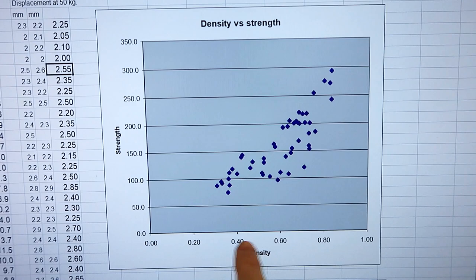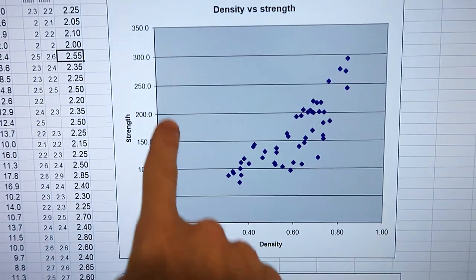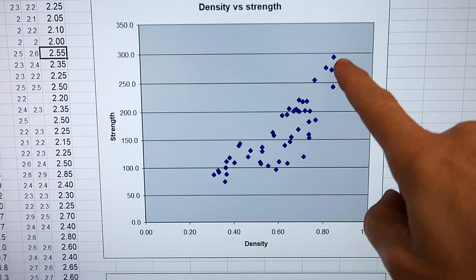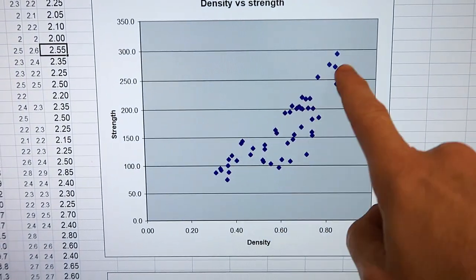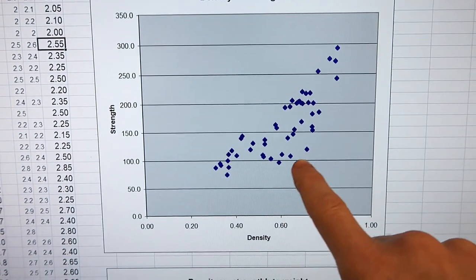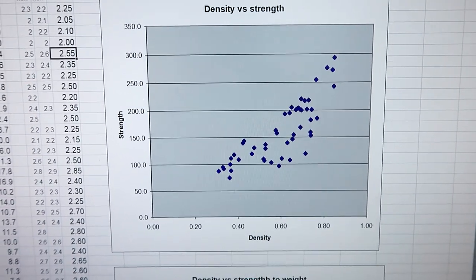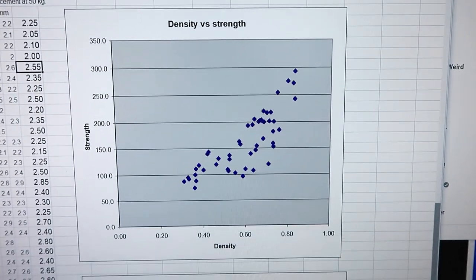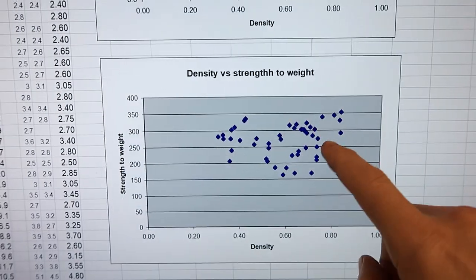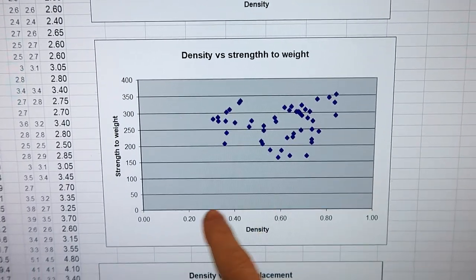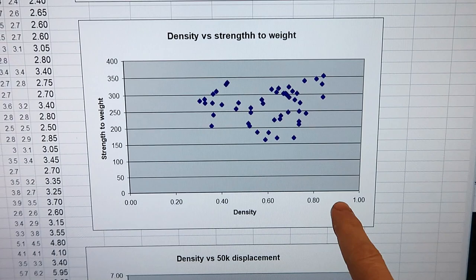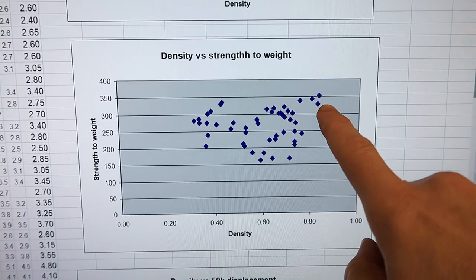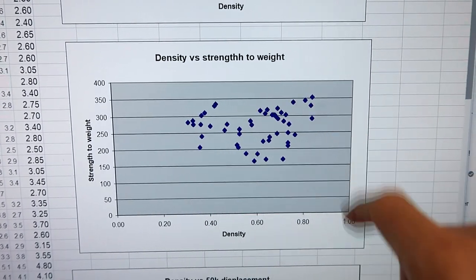And plotting wood density on the bottom versus the ultimate strength, you can see these pretty much follow a line in terms of how well they go. Some of them are suboptimal in that they were heavier but not all that strong. Then I was wondering about strength to weight ratio. So here I've got strength divided by weight on the Y-axis and density on the bottom. And surprisingly, some of the best strength to weight ratios were also the very heaviest woods.